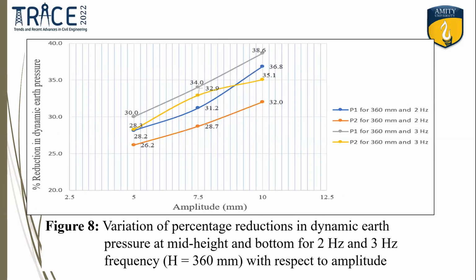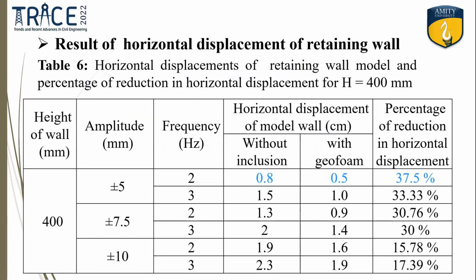The percentage variation for the 360 mm model height follows that of the 400 mm wall model height. Only the difference is that the percentage reduction is more in the case of the 360 mm model height. Result of horizontal displacement of the retaining wall